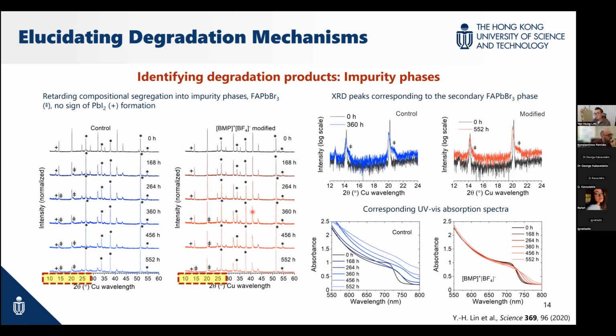I forgot to mention one thing. The perovskite we use is mixed cation and mixed anion. The bromide content is around 25%. And what we see here is that we have different precursor material coming out of the main phase. So what does that mean? We have different anions, so we have iodide and bromide. And of course, this is an iodide-rich perovskite material. When we have this kind of material, it's easier to control its band gap for tandem applications.